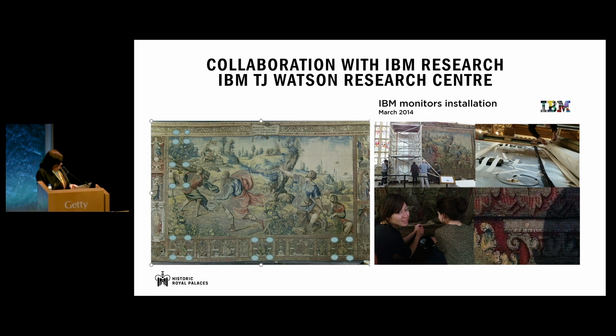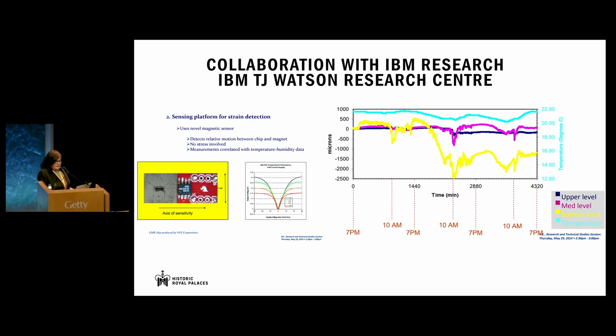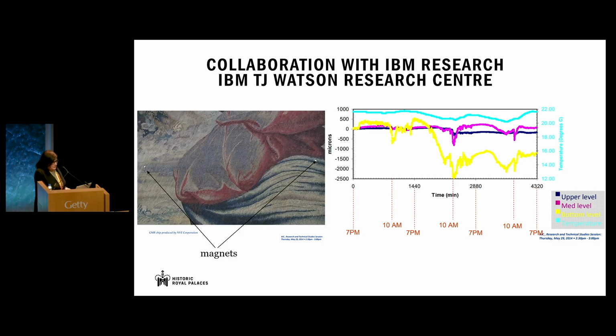And these novel magnetic sensors were detecting relative motion between the chip and the magnet. And here you can see the magnets on the surface of the tapestry, which were almost invisible. The graph on the right shows the results from the sensors positioned at 3 different heights, with dark blue at the highest point, pink in the middle, and yellow at the bottom. And again, we can see that the response is directly correlated to the position, so that the highest point moved the least, while the lowest had the most movement.